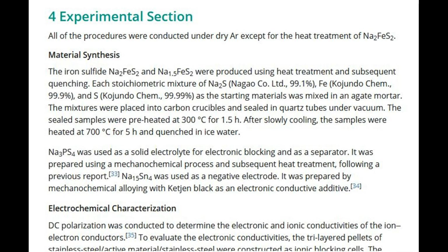All of the procedures were conducted under dry Ar except for the heat treatment of Na2FeS2. Material synthesis. The iron sulfides Na2FeS2 and Na1.5FeS2 were produced using heat treatment and subsequent quenching. Each stoichiometric mixture of Na2S, 99.1%, Fe, 99.9%, and S, 99.99%, as the starting materials was mixed in an agate mortar.